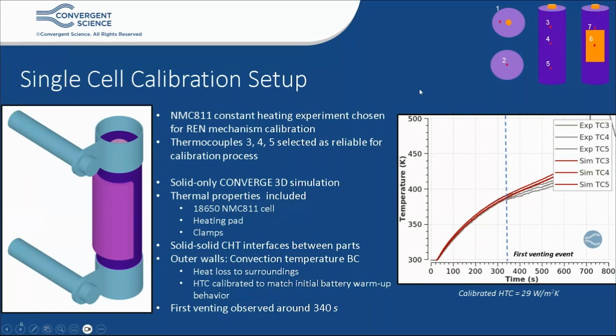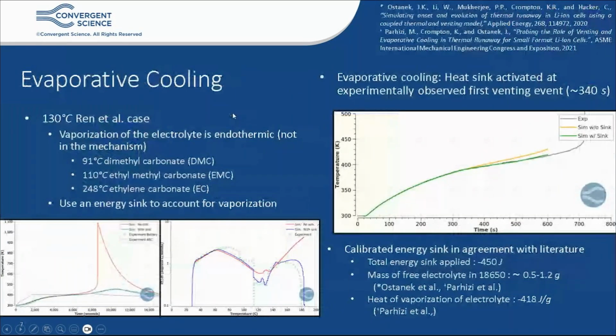And we have come across this in the past when we were trying to validate the REN mechanism. The default REN mechanism does not incorporate a reaction for electrolyte vaporization, which is an endothermic reaction, which absorbs heat. And this reaction becomes prominent at lower temperatures or lower heating rates. When we augmented the default REN mechanism and added an extra energy sink term to account for vaporization, as shown here, we were able to accurately match experimental behavior. This is now also important for the IAV experiments.